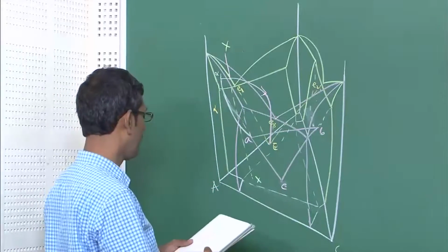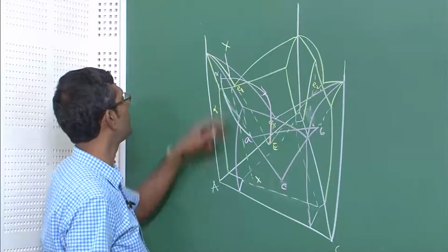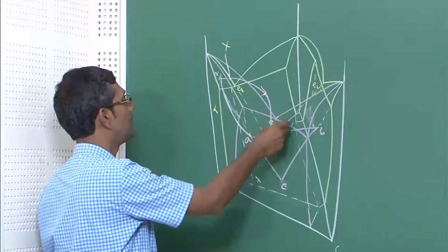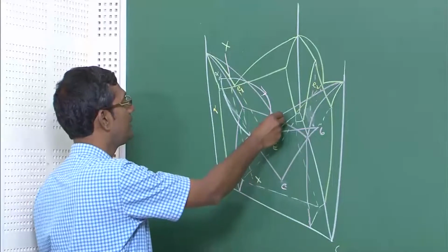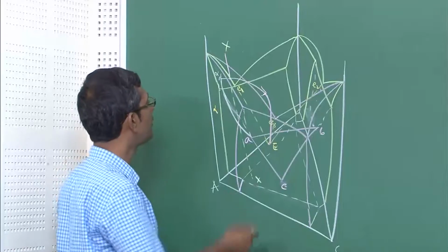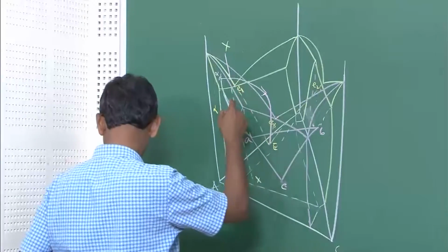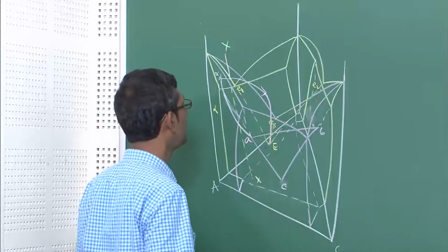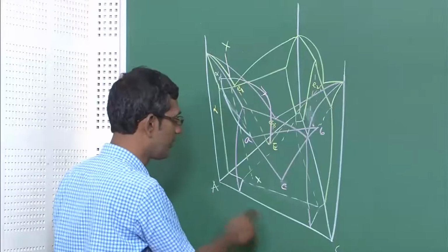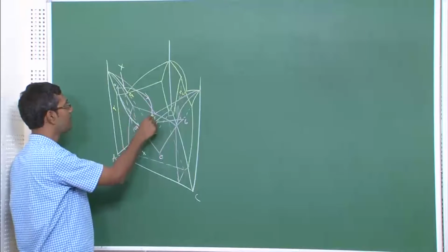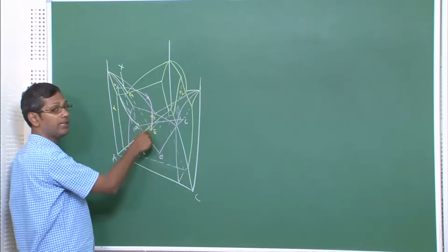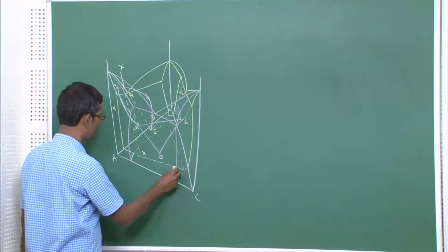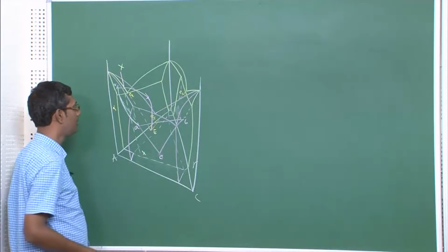But if you look carefully, the first thing it will precipitate is alpha 1, and as it goes down, slowly reaching E3 and E, sorry, it is reaching not E3 here, okay, here it is reaching E3 and E. So, E3 and E is a eutectic between A and C. So, therefore, as it reaches E3 and E curve or the valley, it is going to precipitate both A and C. So, alpha and gamma, this is gamma, alpha and gamma, it is going to precipitate.